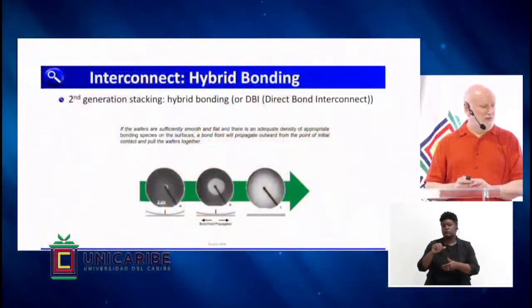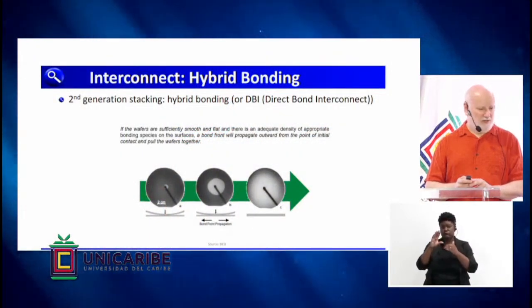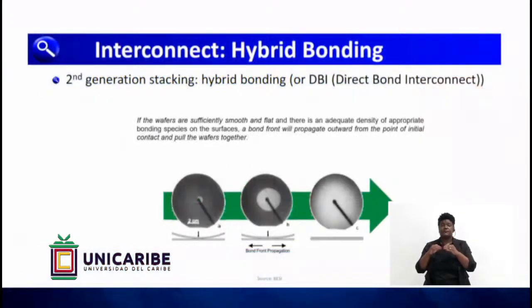This is kind of showing how this progresses. You have to have very, very smooth wafers. You have to have the wafers processed such that the level of the copper is just below the surface of the oxide. So specialized process steps. But once you have that set up, the bonding process itself is pretty straightforward. And you can see here, this is showing that it's kind of a self-regulating process. As soon as you make that first connection in the interior of the wafer, that bond interface of the oxide will kind of continue by itself and spread so that the whole wafer is bonded together.